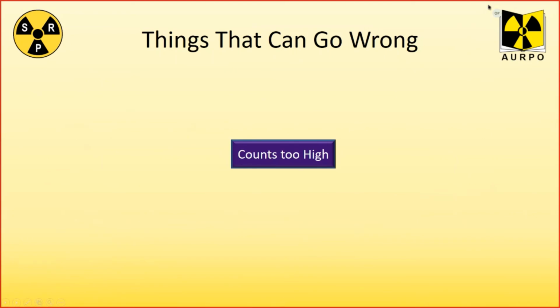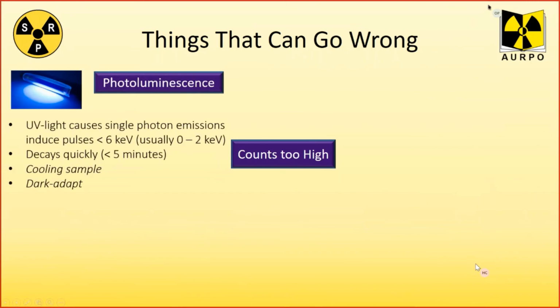So now we know what we can use liquid scintillation for. We're going to discuss some of the common problems that you might find with liquid scintillation counting. If your counts are too high, this may be due to photoluminescence. UV light causes photon emissions, which can interfere with your counts, and these will decay quickly. So the best way around this is to leave your sample in the dark for a while before counting.